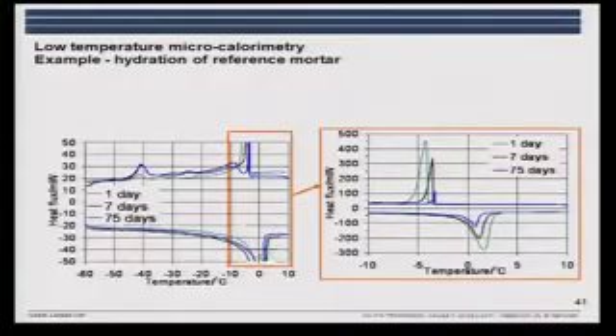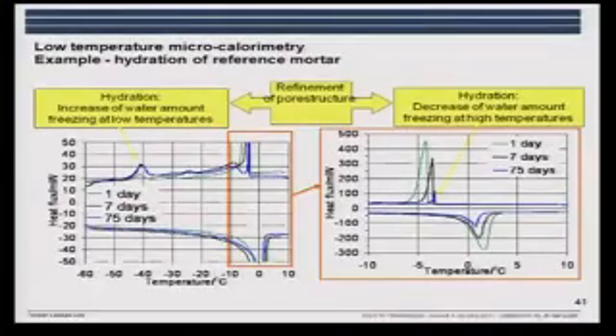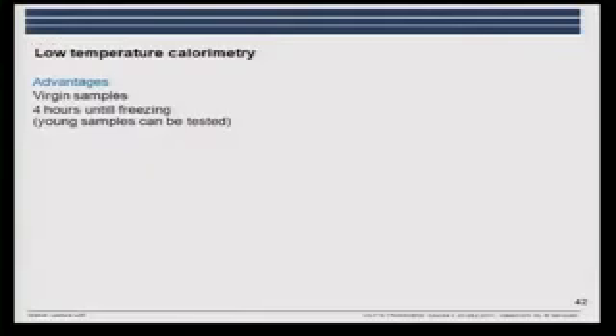And when you're looking at the thawing curve, you can see the development of threshold pore sizes, because there's such a difference between the cooling and the freezing curve. So this is what I said. So we have a refinement of the pore structure.